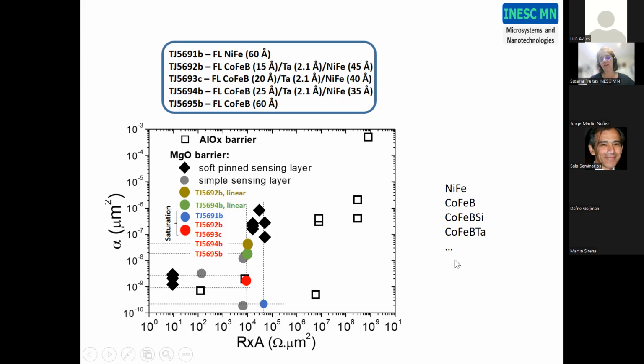The message I want to say is that if we want to optimize materials for the next generation of sensors, we need to be able to find where to change in the full stack, in the materials or in the geometry, where we have the power to change this Hooge parameter. And it turns out that we need to look at different materials. So going away from the traditional nickel iron or cobalt iron boron, and people are looking, and we are also on that family, looking at different materials with softer magnetic properties, but also with high magnetization. So this is very important for the signal to be relevant.